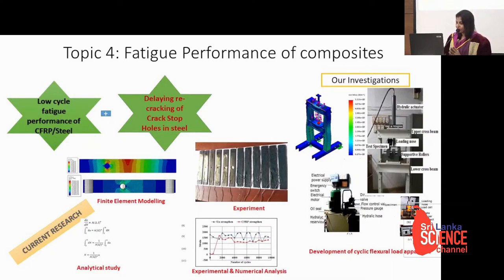We have calibrated it and started our testing under low cycle fatigue. We saw that this system works well for further testing of cracks in crack stop holes, but it is still underway because we haven't done further analysis.